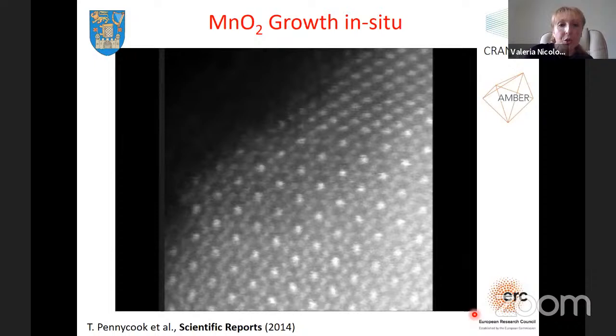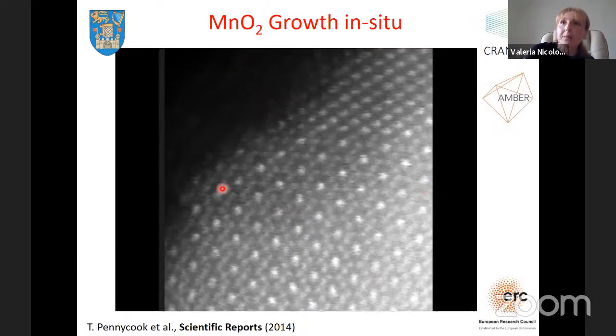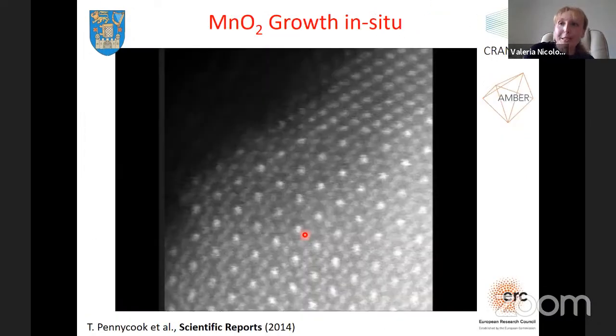Another thing that we could use was aberration-corrected STEM microscopy to really track the synthesis of this material in situ in a microscope. And not sure if it's supposed to be a video starting, not sure if it starts. Well, if there had been a video starting, you could have seen the synthesis of this material happening, and MnO was turning into MnO2 as we went.